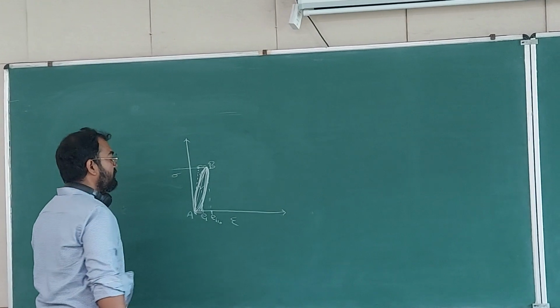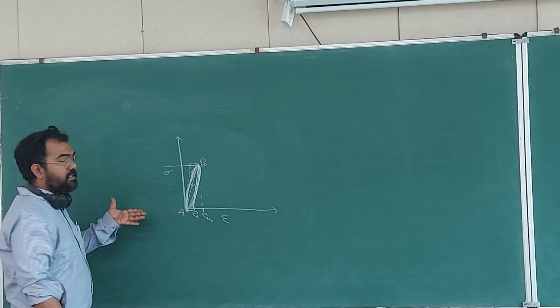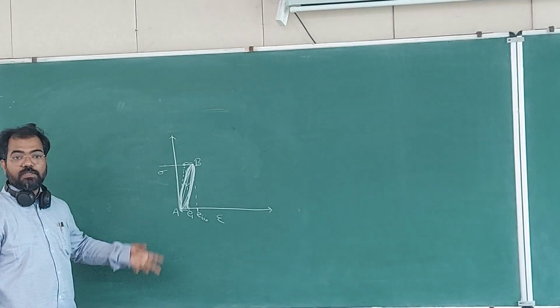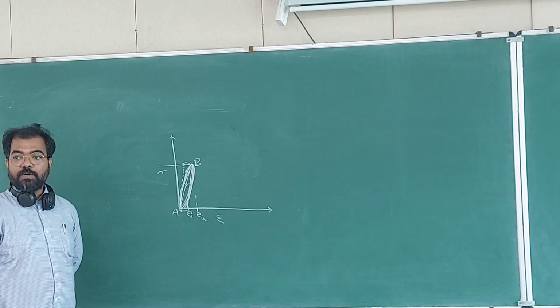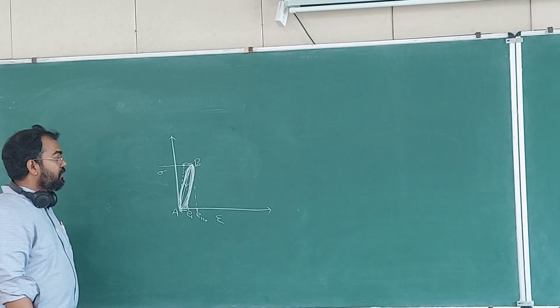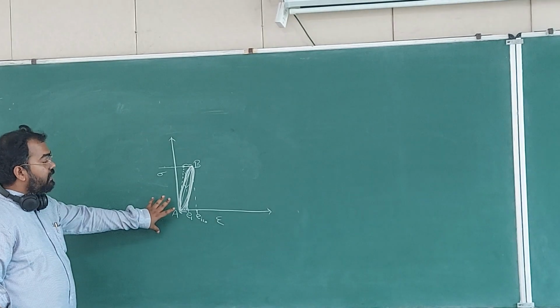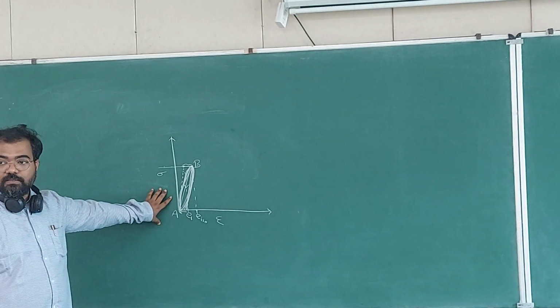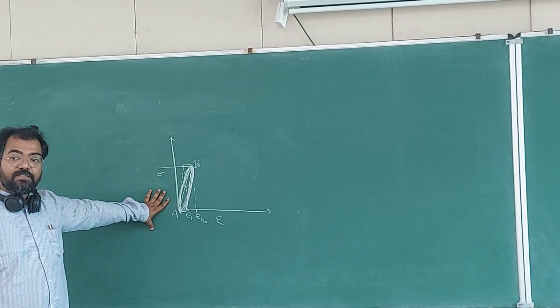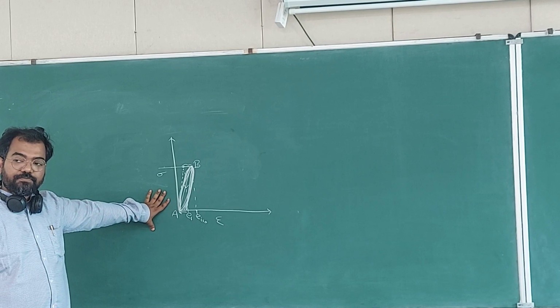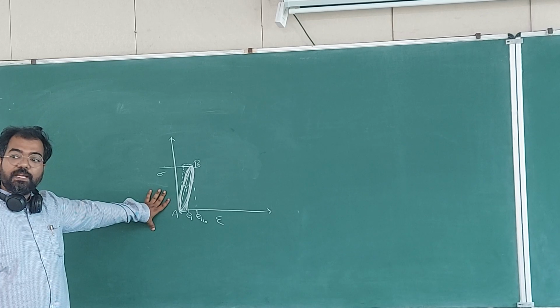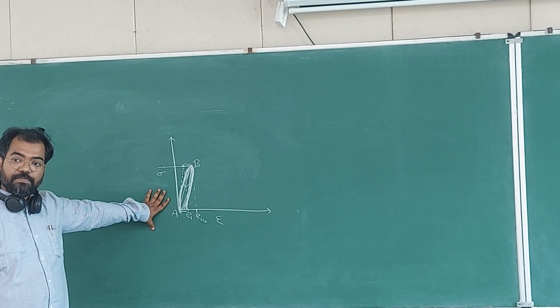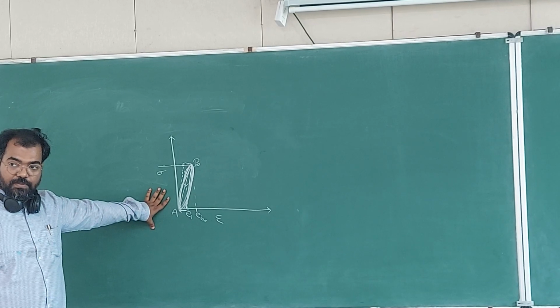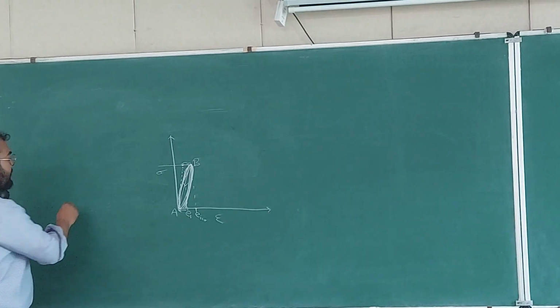So any material can show this effect. It depends on how fast you have to go in order to achieve any significant amount of effect on this. So whatever energy is dissipated in this hysteresis is very small for metallic materials. But this helps for polymers to dissipate the vibrational energy, okay, for damping. And this is called an anelastic effect.